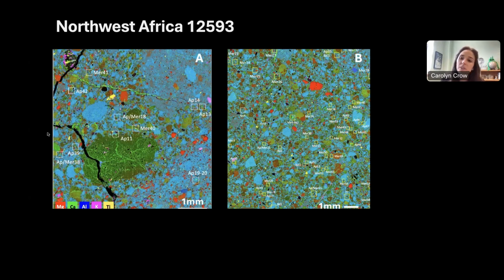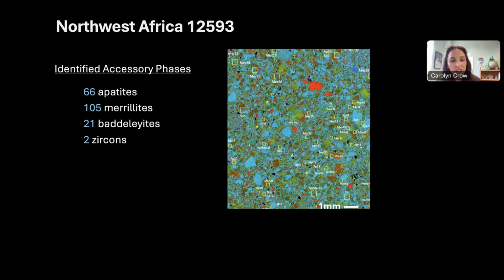Here are two electron microprobe maps of the sample. What you can see is every little square here is an accessory phase or a group of accessory phases, either baddeleyites or apatites. So how many are there? There's a lot. In this 3.5 centimeter slab, we have 66 apatites, 105 merrillites, 21 baddeleyites, and 2 zircons, which is very accessory phase rich for lunar samples.